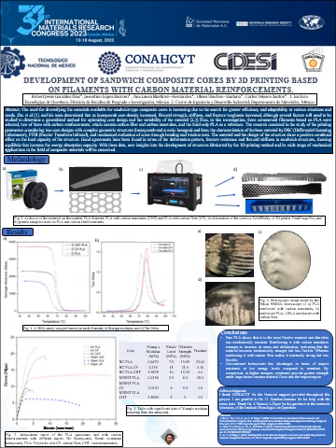The second graph shows tan delta. The tan delta values provide information about the mechanical properties and energy absorption capacity of the different materials. In this case, they indicate that the carbon fiber reinforced PLA has the best properties in terms of resistance to deformation and capacity to absorb impacts, followed by pure PLA and PLA reinforced with carbon nanotubes.